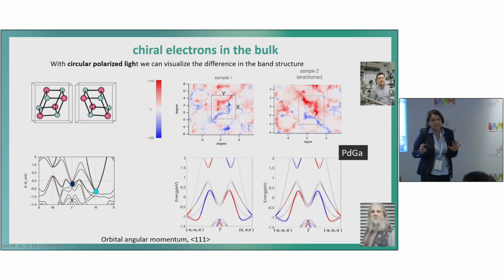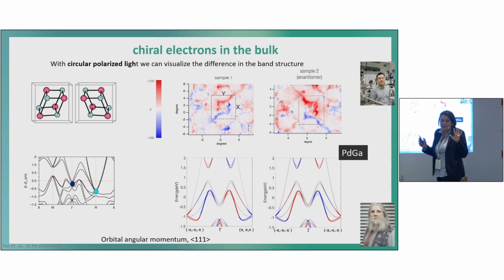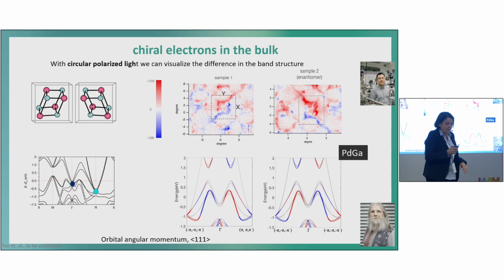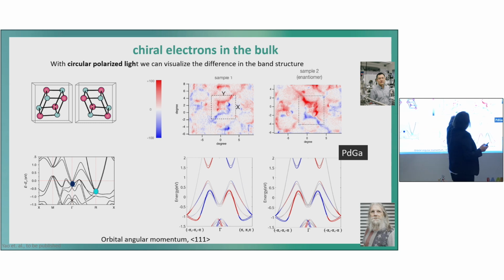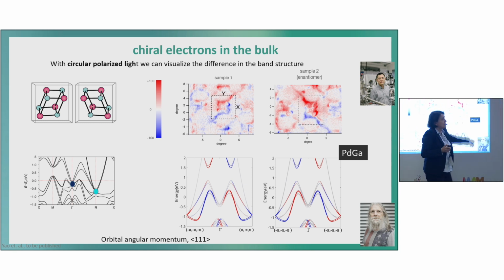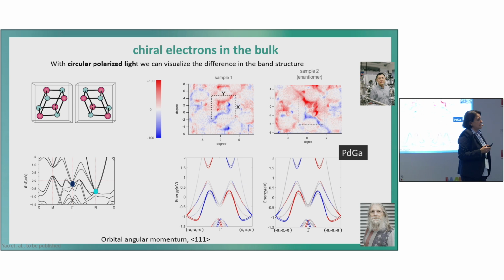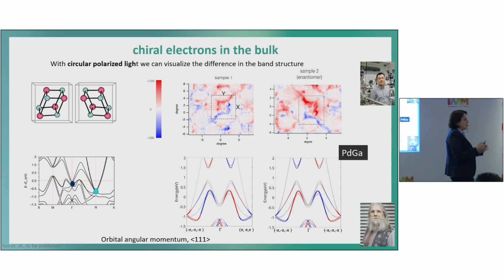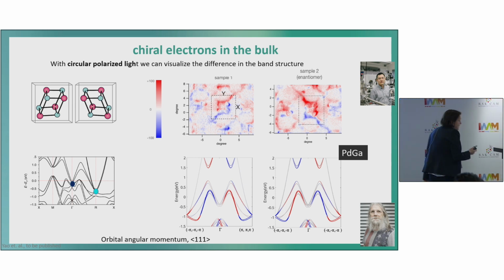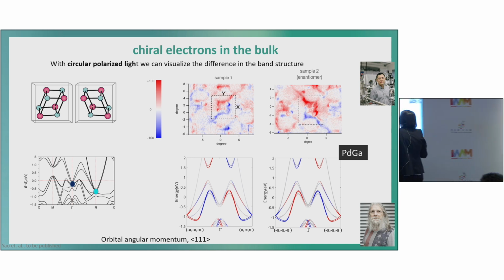This is distinguished, I think, for molecules. We see a difference in the two chiralities of the crystals. And we see it also if we do circularly polarized light photoemission, we see a mirror picture of these two crystals. So this, I think, was quite interesting for us.